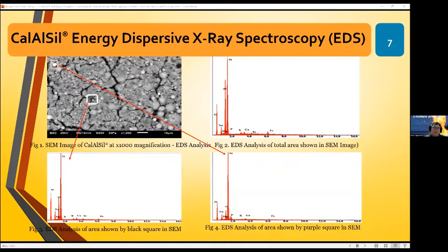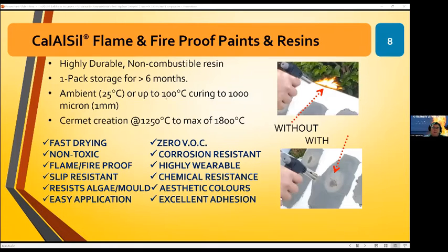Okay, so where this dark spot is here, we took basically where the box is, and found out that it's effectively an aluminosilicate with a little bit of the fly ash style materials in it, much higher aluminium peak in that. This spherical bright ball here is, albeit some of the fly ash behind it was obtained in the EDX measurement, but it's basically silicon and oxygen. The aluminium is far, far less in terms of quantity, and it would generally be a sodium silicate. There's a fair bit of sodium there in comparison to the aluminium, so there's not much fly ash there at all. So essentially, you can start to target these little areas in the mixture and actually get some reasonable chemical information out of the scanning electron micrograph. Just give a very brief overview there.